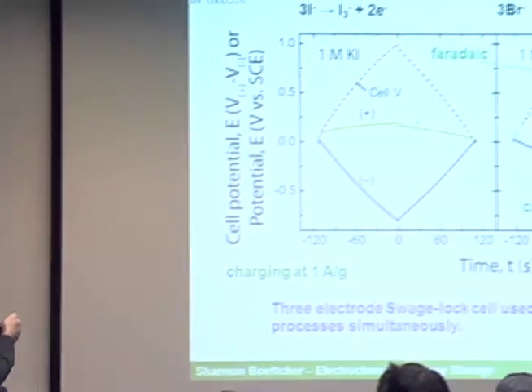But we're also simultaneously measuring the potential of the positive electrode and the negative electrode. The positive electrode potential does not change much with time. The reason is that you have this high concentration of KI, potassium iodide, 1 molar electrolyte, and the formal potential for driving the oxidation of iodide to triiodide is right here. So whenever you put positive charge on that carbon electrode, that positive charge can go into driving this redox reaction.